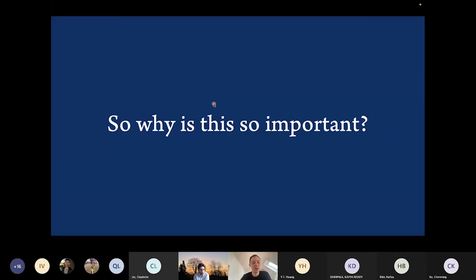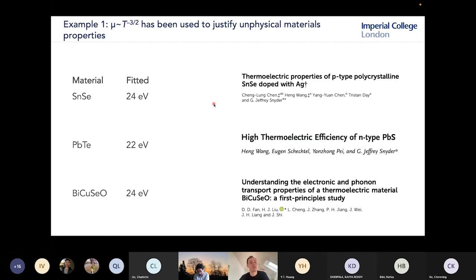Lastly, I just want to say a few words on why I think this is important. This is mainly focused on thermoelectrics, but I think it has applications across other materials as well. The point is that this temperature dependence of T to the minus 3/2 has been used to justify very unphysical materials parameters. Here I'm showing three materials, tin selenide, lead telluride, and bismuth copper oxyselenide, which are classic thermoelectric materials and were long considered to be dominated by acoustic phonon scattering based on their mobility dependence. Based on that, in order to reproduce the experimental results, people had to fit very large deformation potentials to match the experimental mobility, around 24 electron volts.